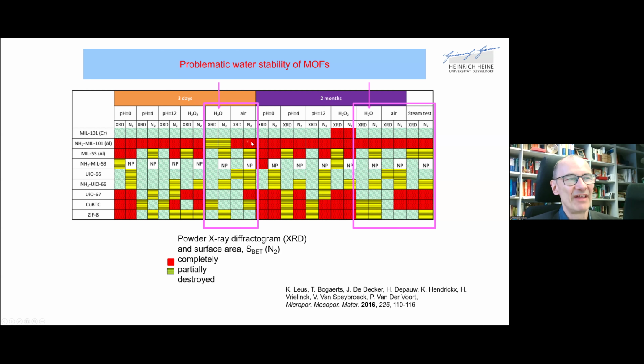So if you see here the red squares or the hatched yellow squares, that means that the MOF is completely or partially destroyed. And for many of these exemplified MOFs here, you see these red or hatched yellow squares. There's only one MOF or a few that stick out. Important here is MIL-101 because it is stable in many of these conditions which were applied here, and to some extent maybe also UiO-66 and UiO-67.